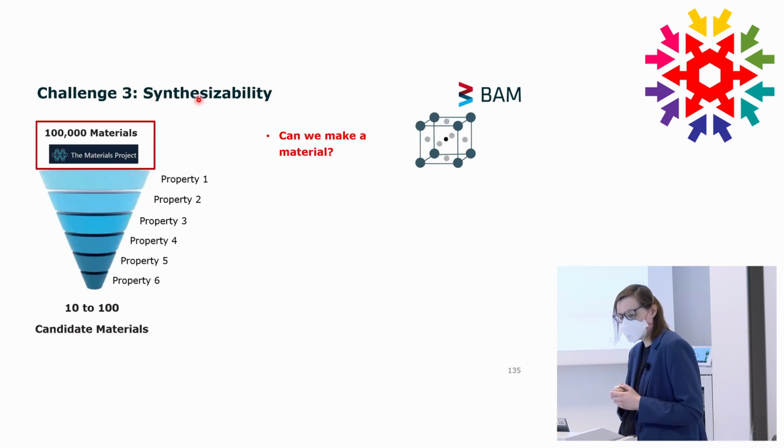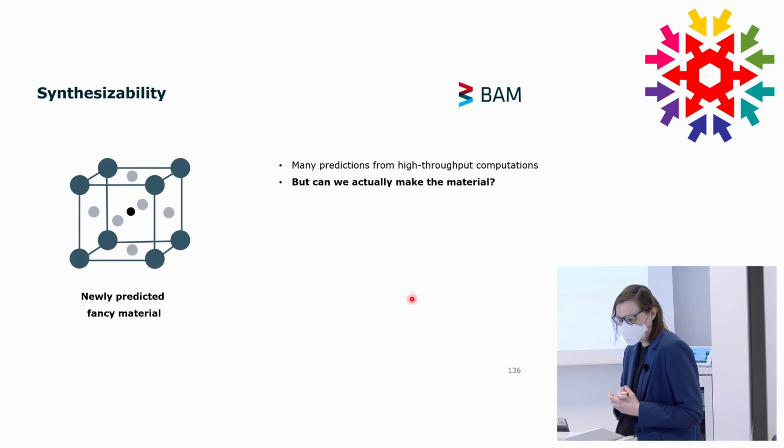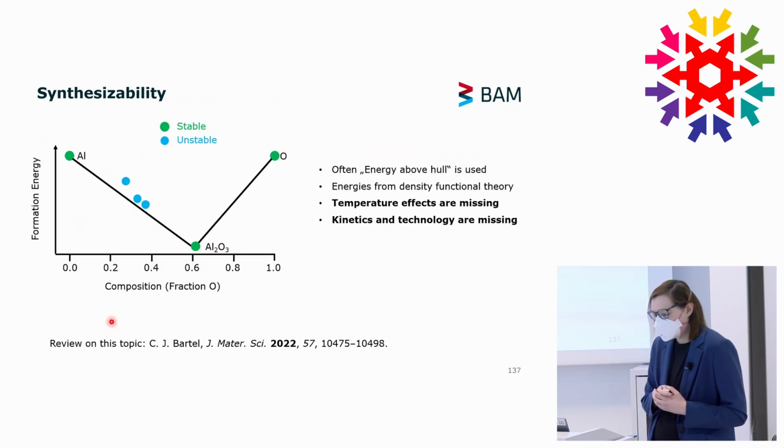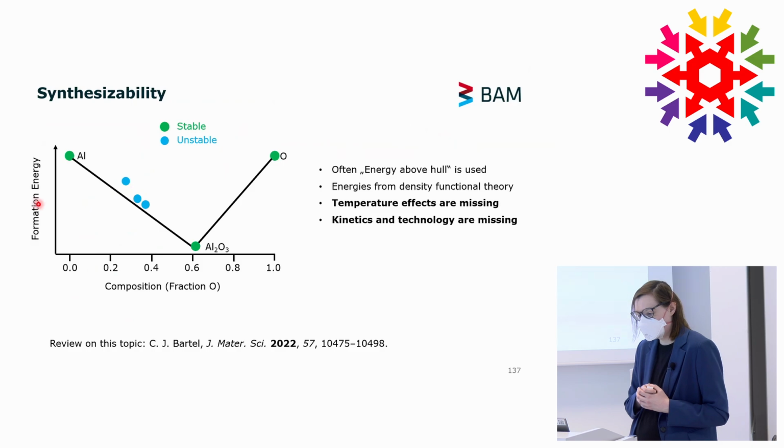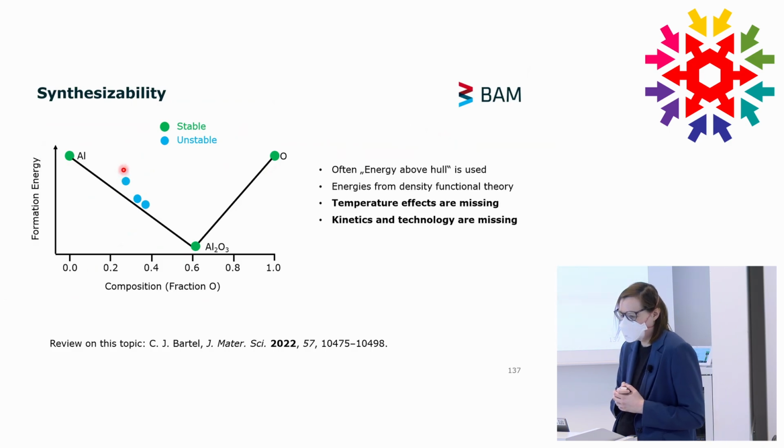Now I'm coming to the last topic. And this is now about synthesizability, right? In case we have now decided on a new structure, the question is, can we actually make the material? Very often, to decide this, we of course use the formation energies as a function of the composition, right? You put in all known phases and their formation energies, and then when you have a new phase, you check how far away you are from the hull, right?